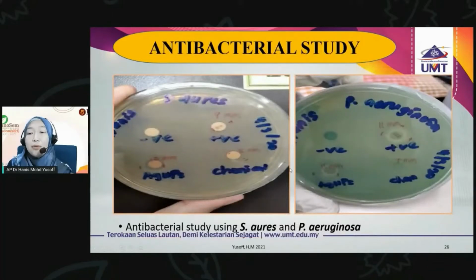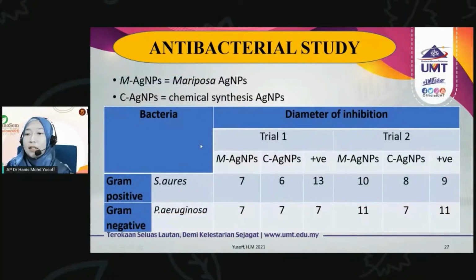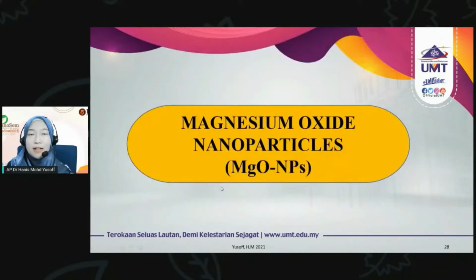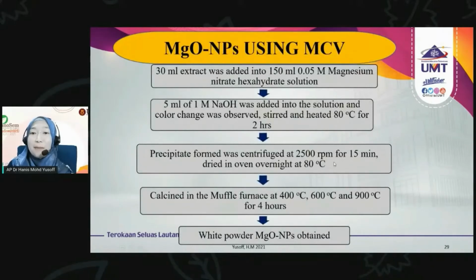As for the antibacterial study, we only managed to study towards S. aureus and P. aeruginosa. These were carried out by a final year project student just before the first MCO, the first pandemic. Then a lot of experiments were pending, so we just use what we have. There were 2 trials that were managed to be carried out, and we also compared with chemically synthesized silver nanoparticles. For the first trial, it seems comparable, even though it's a bit low. But for the second trial, the green synthesized silver nanoparticles exhibit larger inhibition compared with the chemically synthesized silver nanoparticles. Okay, so that's all for silver nanoparticles. I will proceed to the next metal oxide, magnesium oxide nanoparticles. Okay, so this is the method.